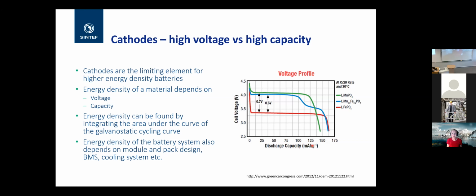But if you look at the energy density, that depends on both the capacity and the voltage. So if you have a battery with high voltage but low discharge capacity, your total energy density would be lower than if you could increase the discharge capacity. So the energy density is essentially the integral under the curve, or you can integrate the area under the curve of the galvanostatic cycling curve. But of course, if you do a quick calculation on this curve, you will find an energy density which is over 500 watt-hours per kilogram.